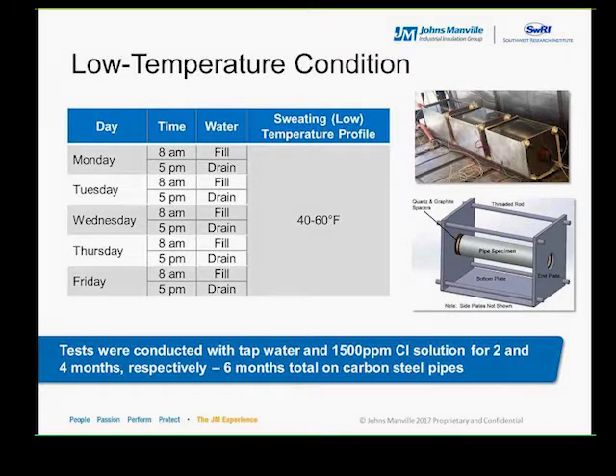So to begin, and so that everybody's clear on the details of the conditions that were tested, the first set of data that I'm going to be talking about is what Leo referred to as the low temperature conditions. So this profile kept the pipe between 40 and 60 degrees F during the entire 6-month test protocol. In this manner, the installation and assembly remained wet the entire time. Each day, the sample setups were filled with water in the morning and then drained at night. One thing that's really important to point out is that for the first 2 months, tap water was used to fill the chamber, as can be seen in the top right picture, and in the last 4 months, a 1500 ppm chloride solution was used to further accelerate the condition of corrosion under insulation.